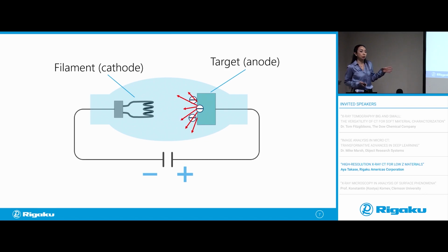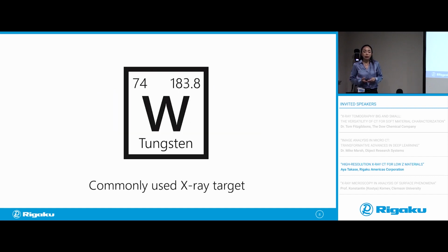What we're interested in here is the energy distribution of those X-ray photons. That energy distribution depends on the target material and the applied voltage. For the target material, you can use different types of materials, usually metals. You need to have something that has a relatively high melting point because the electron beam is going to heat the target quite a bit. Tungsten is probably the most commonly used X-ray target for X-ray imaging. We use tungsten because its atomic number is 74. It has a lot of electrons and it has a high melting point. Those two factors help you to produce a lot of high intensity X-rays.